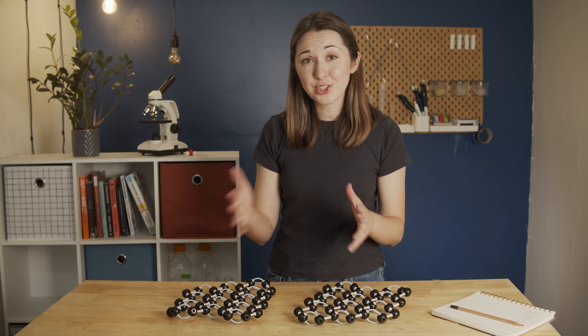For the next big potential carbon innovation, we go back to the graphene sheets from our pencils. Lots of groups are working on making single-layer sheets of graphene, and while it was first successfully accomplished in 2004, it's taken a while for production to reach a stage where we can do it efficiently enough for useful products. The current best strategy is chemical vapor deposition — like nanotubes, it involves a thin substrate layer coated in a catalyst inserted into a furnace, a carrier gas like methane is added, the high heat decomposes the methane into carbon, and the carbon deposits onto the catalyst layer to form a single atomic layer of graphene.